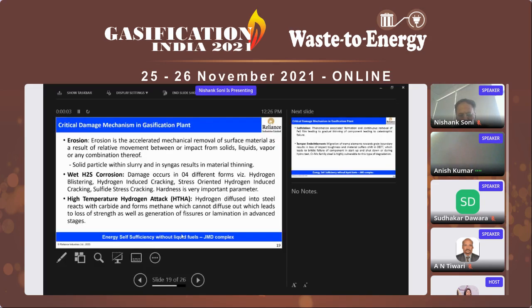In this case, damage occurs in four different forms, which are hydrogen blistering, hydrogen induced cracking, stress-oriented hydrogen-induced cracking, and sulfide stress cracking. These damages are very related to the hardness of the particular material, and the hardness value of the material is very important with respect to the occurrence of all these damage mechanisms.